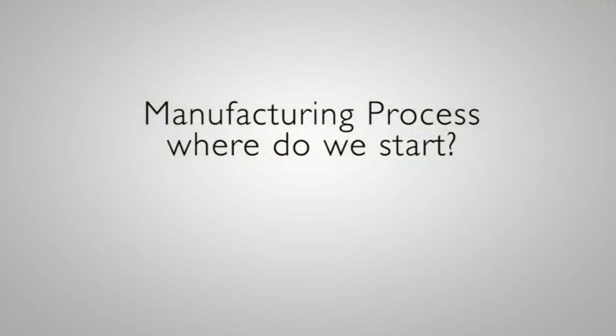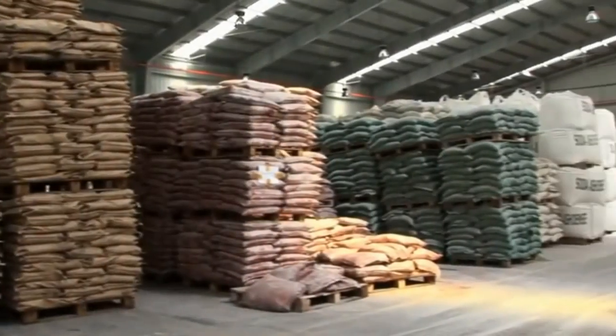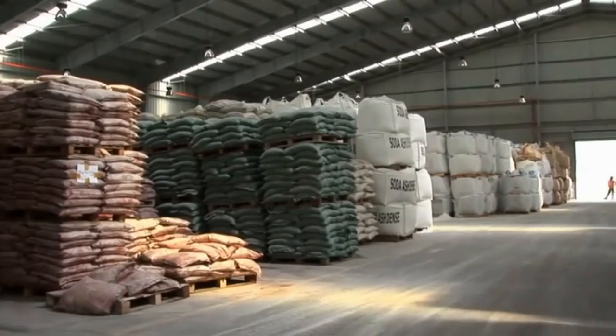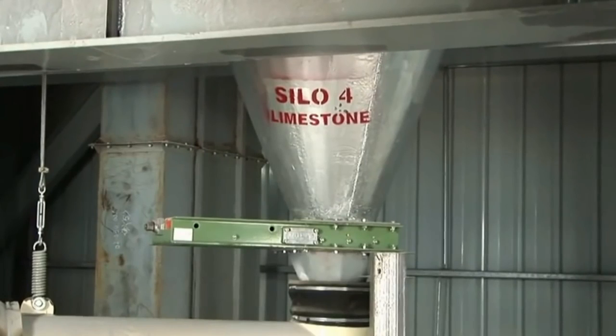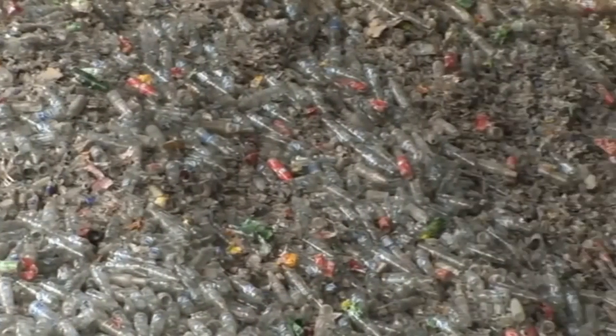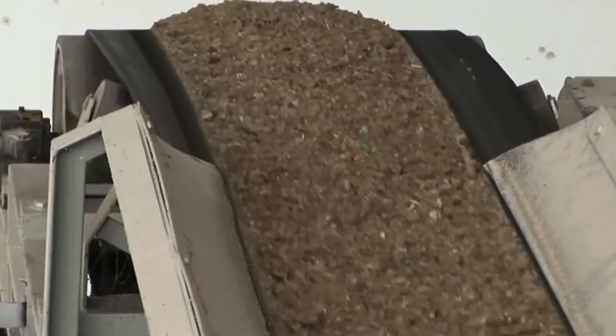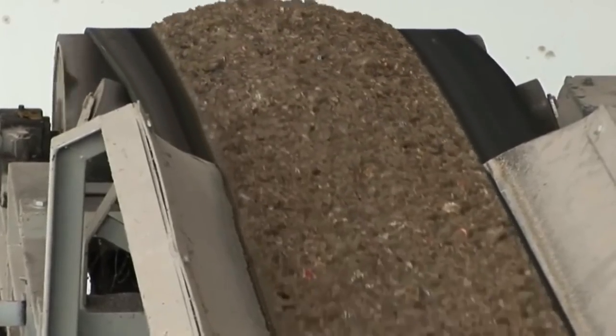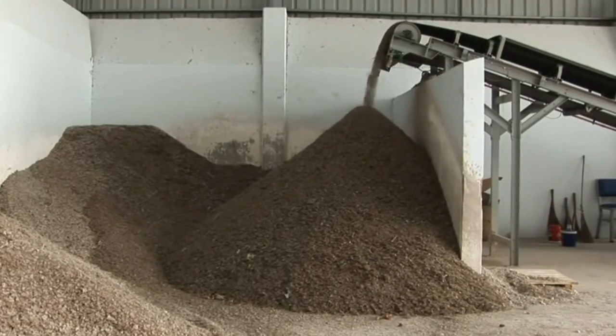Manufacturing process. Stage 1: Raw materials. The major raw materials used in glass container production include sand, limestone, soda ash, and cullet. Cullet is recycled glass that helps to reduce the amount of raw materials needed to make new glass. Cullet provides an important energy saving by lowering the temperature required for the melting process, helping to reduce greenhouse gas emissions.